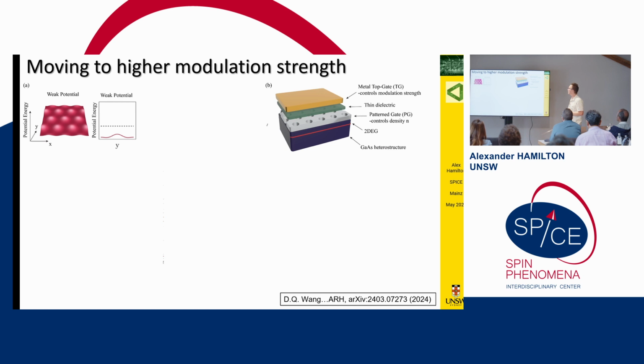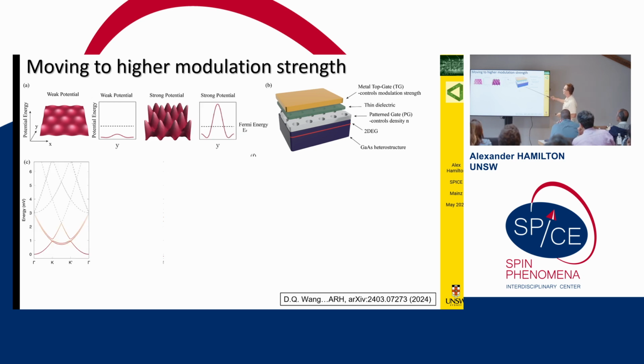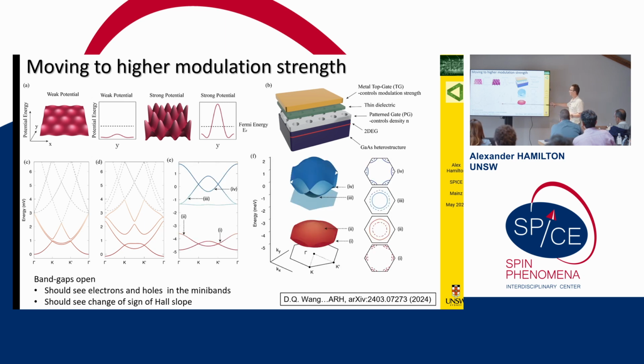So we keep the same devices. Before, essentially we had a weak potential, the electrons traveling along are scattering off this weak potential. Now what we want to do is go to a strong potential. And so our band structure goes from not having any gaps and being basically free electron-like with some structure in it to, we want to see if we can form these Dirac points, and if we make the modulation strong enough, we should open up a gap and form a flat band. And so these are the calculations of what the band structure should look like for the sort of voltages that we can apply in experiment.